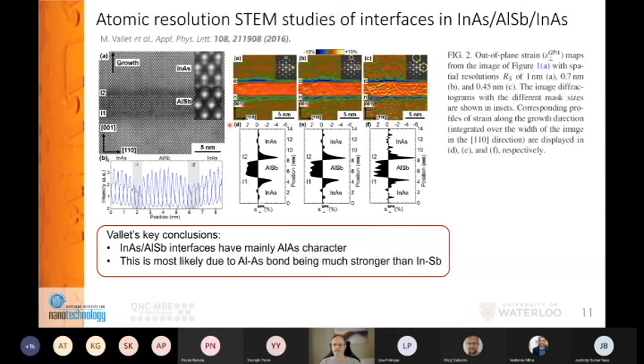Now, the problem with TEM: we all love seeing the individual atoms or columns of them, but by the time you make the sample, which is very thin, many things can happen. During the measurements, electron beam damage can happen. The sample, because of all the strains, elastically relaxes, so the atoms expand. So basically, there's no certainty that what is being studied here is indeed what's happening in the bulk material. That prompted us to take a different approach and first see if we can answer some of the questions about those interfaces in a way which doesn't need to go into very sophisticated techniques at this point.